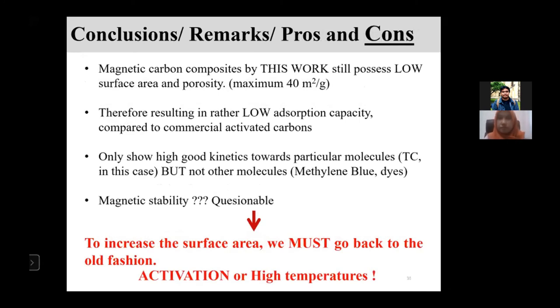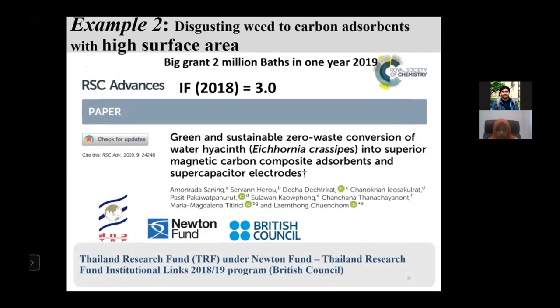But still, we have a problem, because if we want to sell to a company, they will say you still have low surface area, so you can improve it to adsorb a lot of molecules as well. And we found later that our adsorbent doesn't work well with other pollutants like methylene blue or other dyes. So it is specific only to tetracycline, which has a lot of hydrogen bonding. If you play with other ionic molecules like methylene blue or methyl orange, it really doesn't work quite well. So it's still a question what actually happened and what kind of functionality we need in this case.